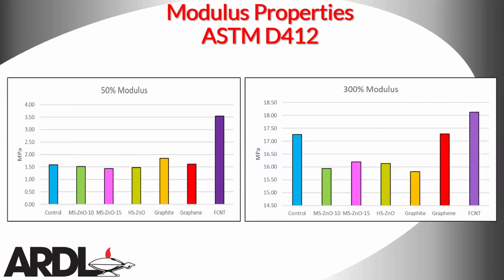Now, if we get into our modulus properties, we looked at each side of the spectrum. So we looked at 50% modulus and 300% modulus. So the first graph here, looking at 50% modulus, you can see that you see very little difference with the zinc oxide. They're very similar to the control. The graphite actually saw a slight increase in 50% modulus. The graphene saw no change from the control, but you can see a huge increase in the 50% modulus with the functionalized carbon nanotube. It is over double what the actual control is.